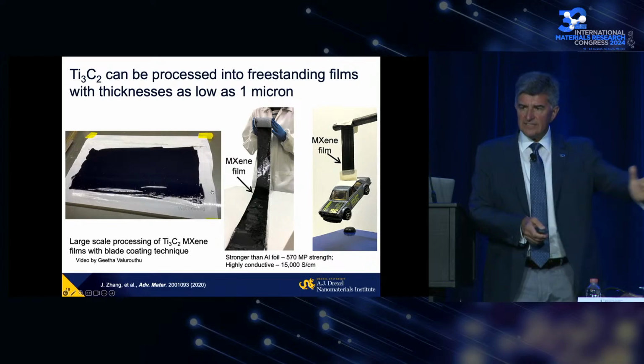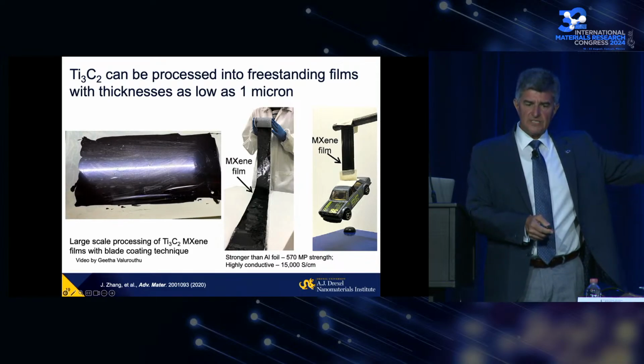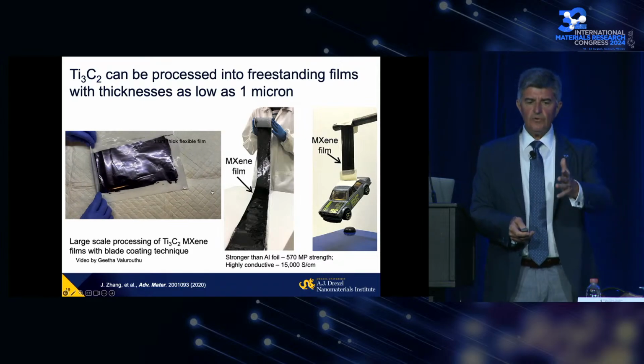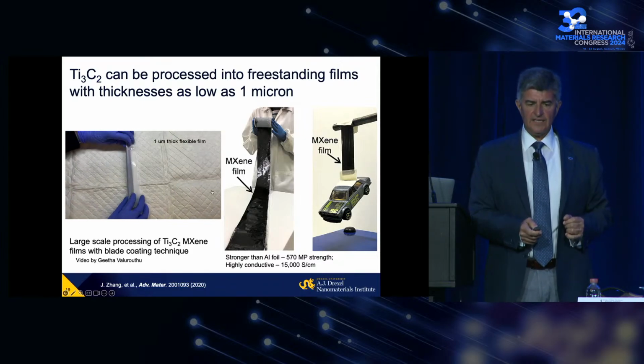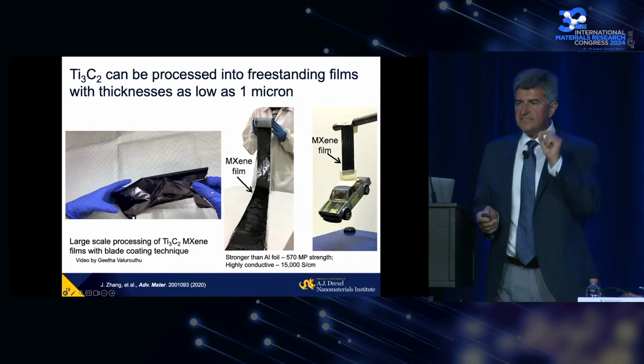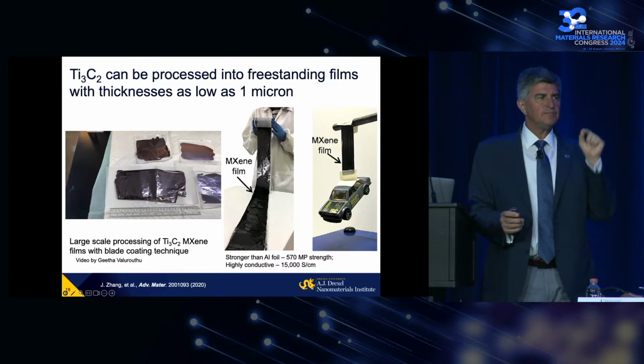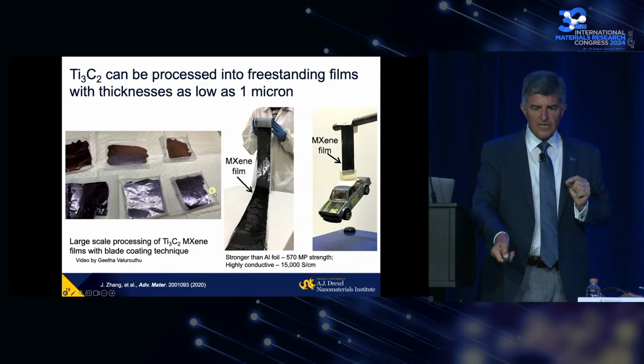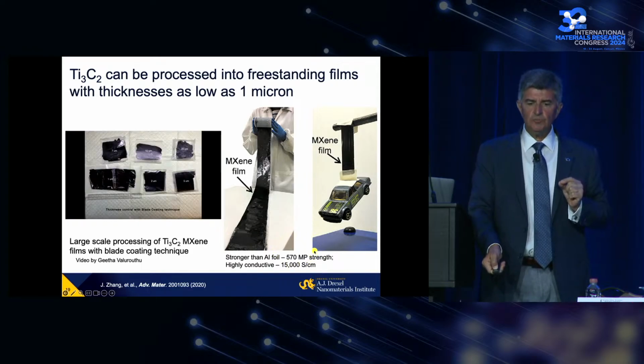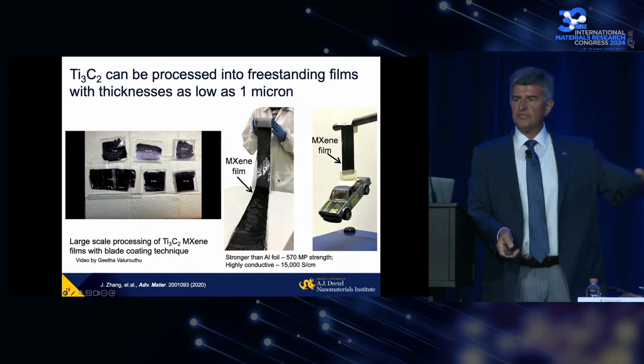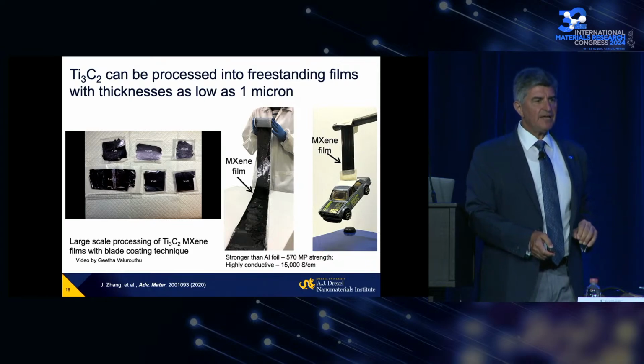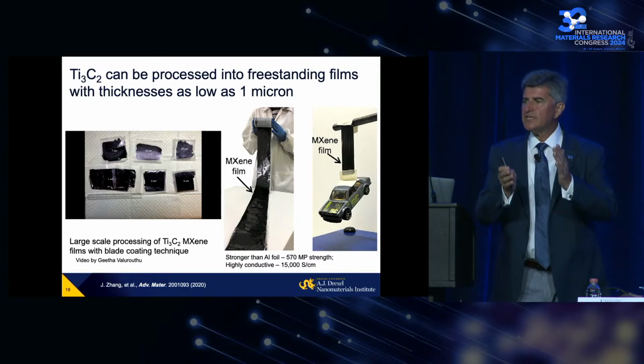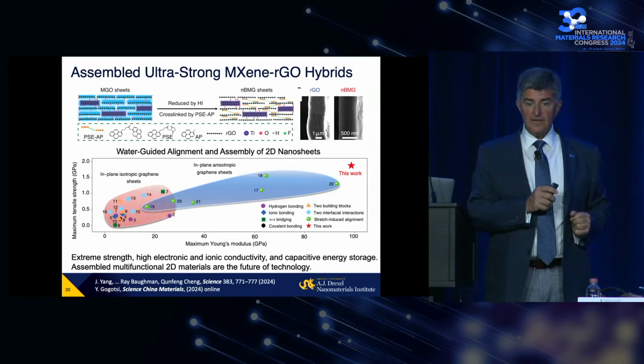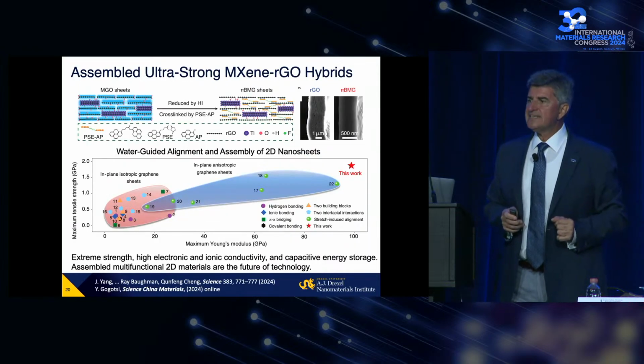This is my student just spreading the liquid crystalline MXene solution on the surface, letting it dry, and now she separates this from a hydrophobic PVDF film. You see, this is a 1 micron thin film, and it actually has the mechanical strength of good aluminum foil. After drying, it is highly conducting. Imagine, for example, a current collector for batteries: instead of 10 or 15 micron metal, copper or aluminum, you can have a micrometer thin film and shrink the battery this way. But this is definitely not the best one can achieve.